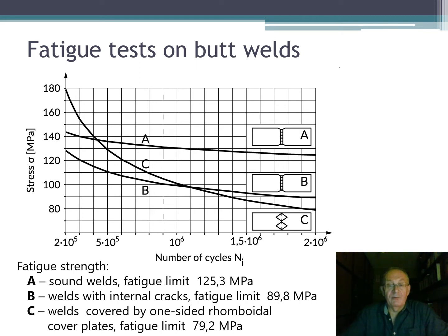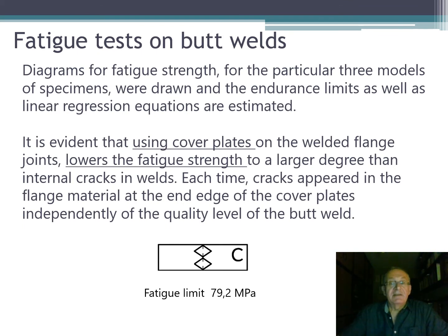So such a solution with rhomboidal cover plates was used in early railway bridges to strengthen the butt joint. It was the intention, but it is evident that using cover plates on the welded flange joints lowers the fatigue strength to a larger degree than internal cracks in the welds. So the fatigue strength is lower than for welds with cracks. Each time cracks appeared in the flange material at the edge of the cover plates, independent of the quality level of the butt welds.